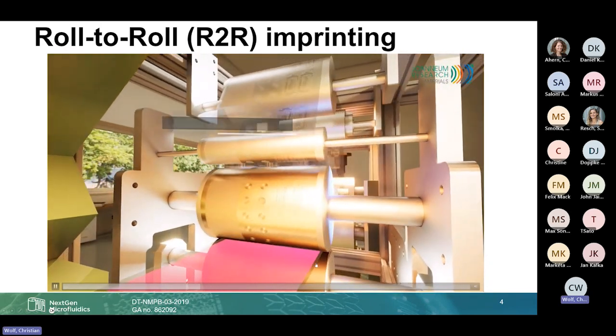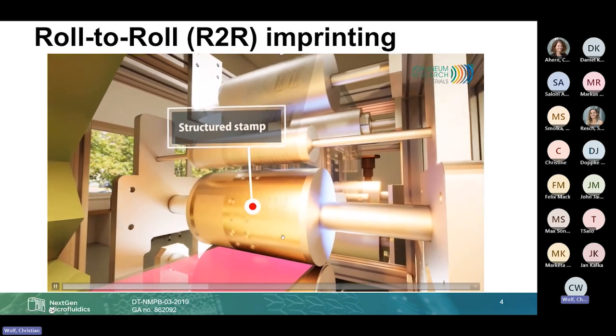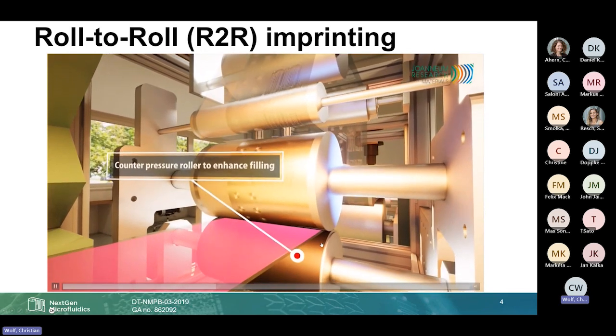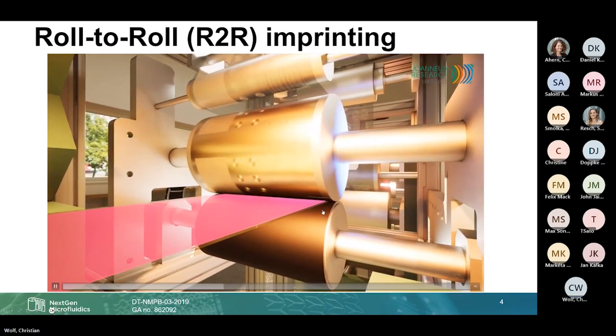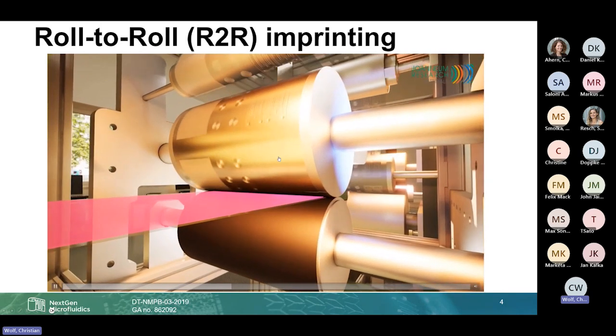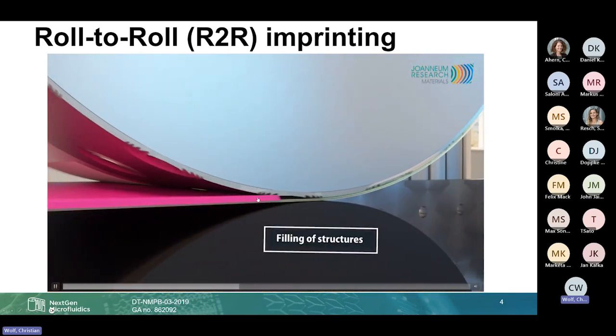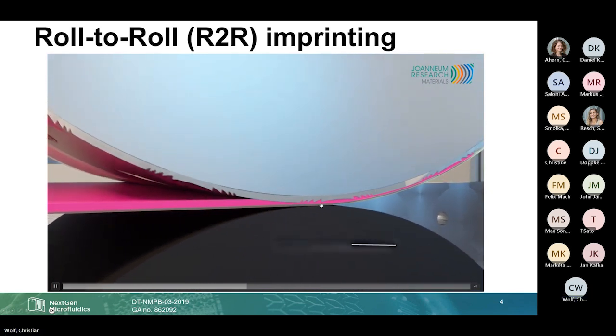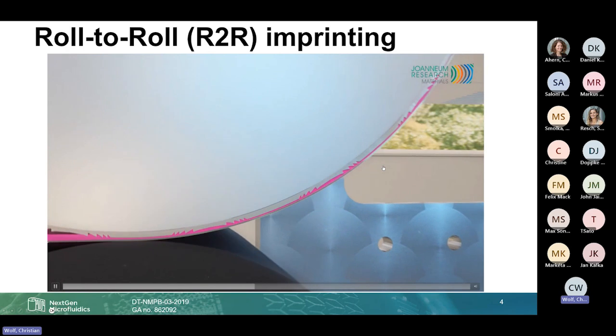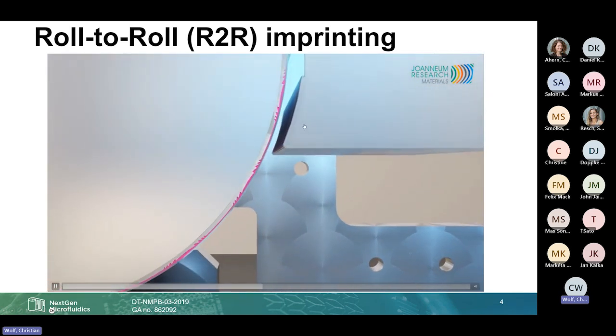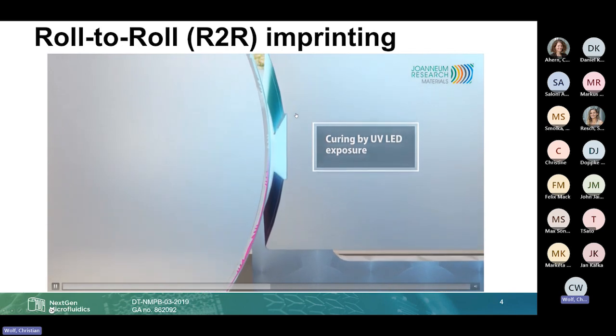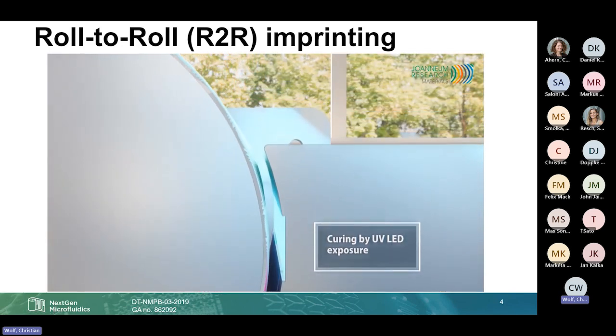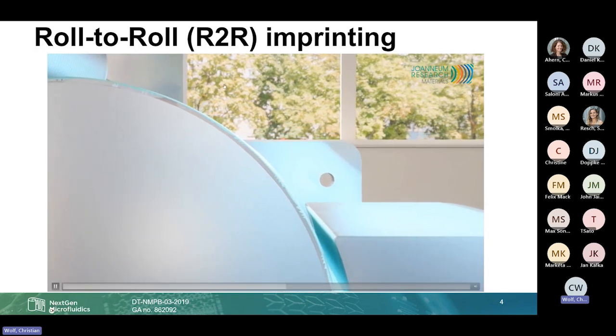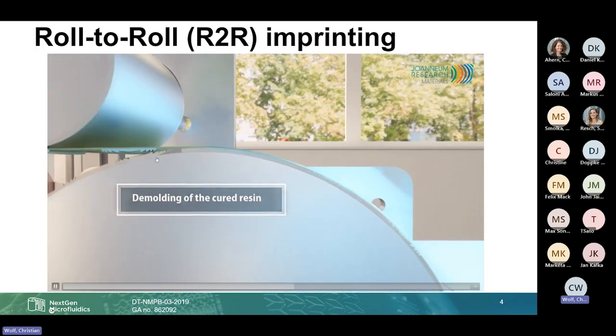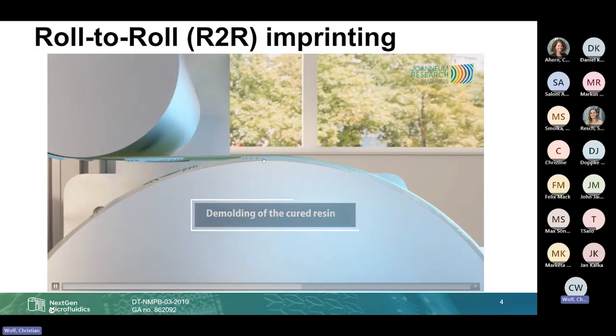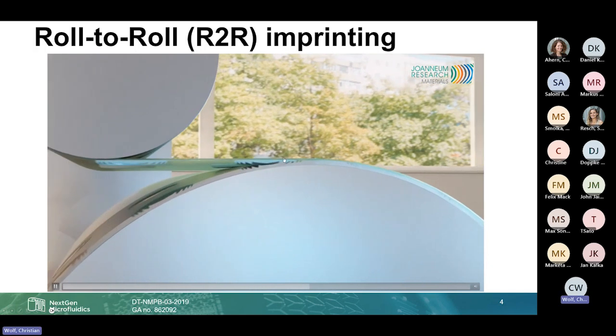And this thin film is then transported between two rolls, where one has a structured stamp on one side. Then you can press these structures on your roll into the still liquid resin film. And while the resin and the foil are still on the roll, they are cross-linked and hardened from the backside by UV light. That's also why it's important that the foil is transparent. After half a turn, the resin is fully hardened and you can demold your structures from the roll, as you can see here in this animation.